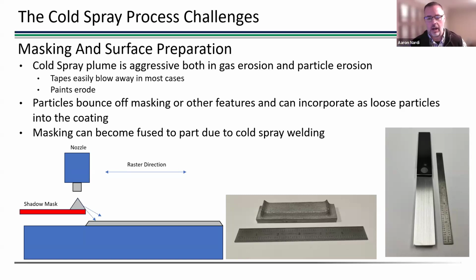So the last image there on the right is an example of where we're purposely doing that. We have a steel piece of sheet metal and an aluminum piece of sheet metal, and we've created an overlap joint, and then we've welded the two together with cold spray. In this case, it was purposely done. We wanted a good bond joint, but you can kind of see that this process not only can be used for coating and additive like we're all doing, but it also does secure materials together. Not exactly the same way as fusion welding, but it does do the job.